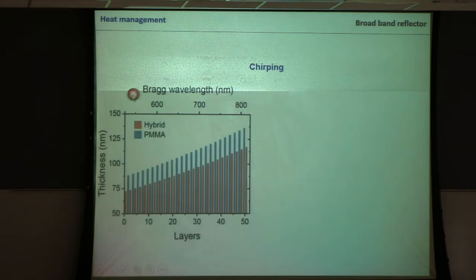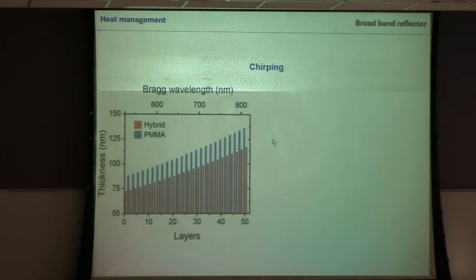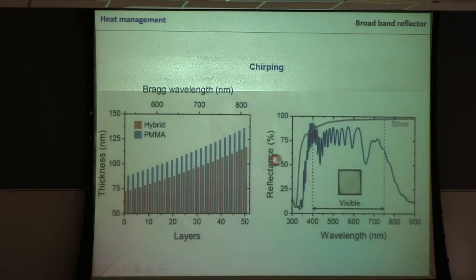So how can we get to broader reflection bands? I showed you we can increase the refractive index contrast. With our materials, eventually we get into an issue because I'm not sure how much further we can push our hybrids than 2.1. But an option is just to use chirped mirrors, meaning we use mirrors where with increasing layers, the layers have thicker layer thicknesses. So we introduce by default a mistake in our mirror fabrication. And when we do that, we massively increase the reflection band.